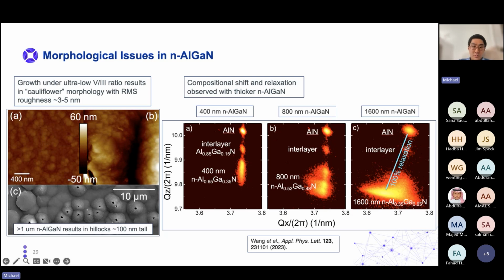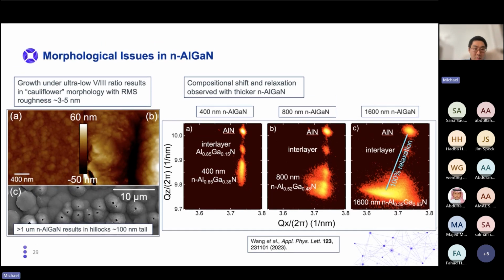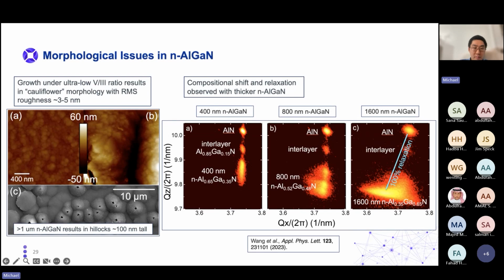you observe a drastic blowing up of the morphology. So at 400 nanometers of N-type aluminum gallium nitride, the N-type aluminum gallium nitride is growing in this almost cauliflower-like morphology with a roughness of around 3 to 5 nanometers RMS. But as you grow thicker and thicker, over here you see 1600, this is 1600 nanometers of n-AlGaN. And you can see that the roughness just goes off the charts. It results in larger than 100 nanometer tall islands.